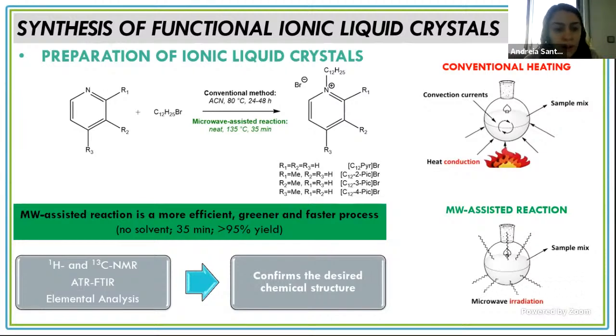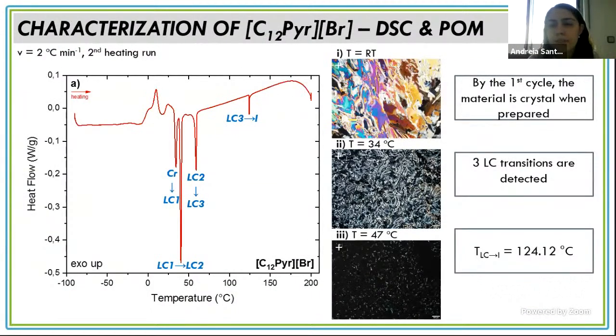All prepared compounds were characterized by proton and carbon NMR, FTIR, and elemental analysis in order to confirm the desired chemical structure. In order to study the liquid crystalline behavior of all ionic liquid crystals prepared, DSC and POM analyses were performed. For C12 pyridinium bromide, in the first cycle, the material is crystal when prepared, and in the second heating, 3 different liquid crystalline transitions were detected. The first one at 25 degrees, the second one at 35 degrees, and the third one at 60 degrees. The isotropization was at 124 degrees.